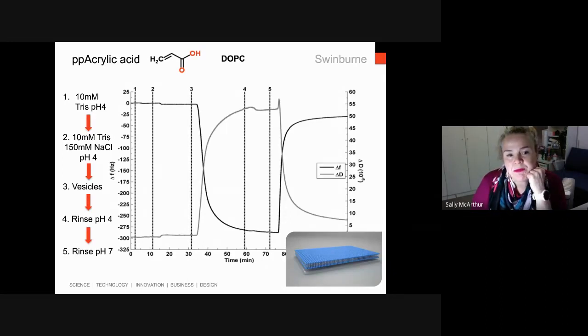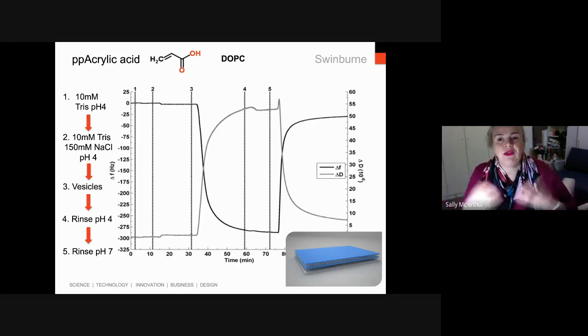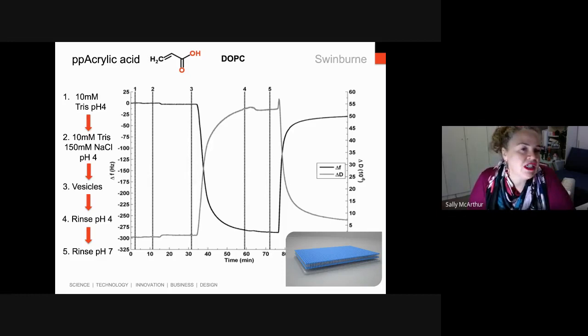And pH is an important factor because of the surface charge of the acrylic acid. At pH 4, it's neutral, so that allows the vesicle to go down onto the surface. And then at pH 7, the surface becomes slightly charged, but the vesicle also changes its characteristics. And that driver, that osmotic pressure with that change in pH, actually drives the collapse of the vesicle onto the surface to create this monolayer.